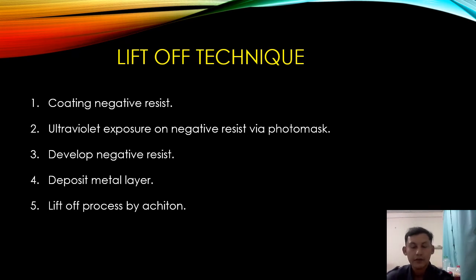The steps needed for the fabrication of the SAW device are: first, coating the negative resist. Second, ultraviolet exposure on negative resist via photomask. Third, develop negative resist. Fourth, deposit metal layer. And lastly, lift-off process by acetone.